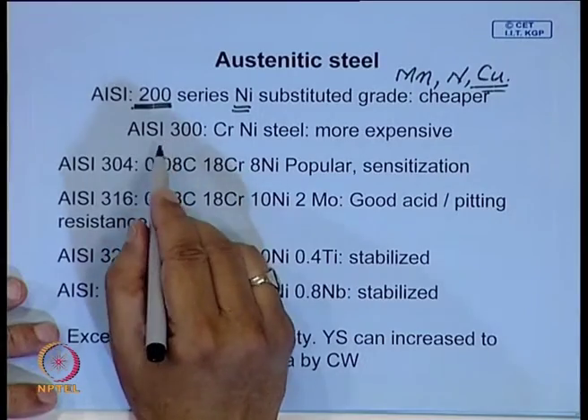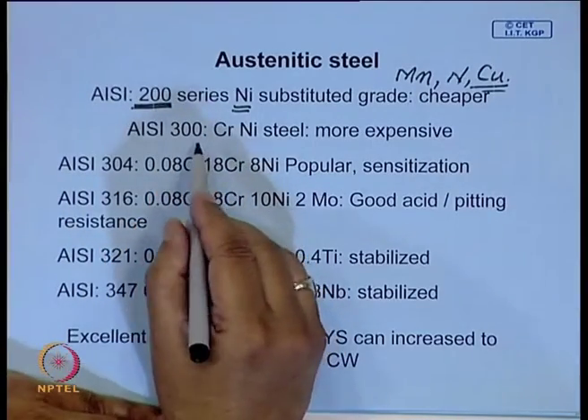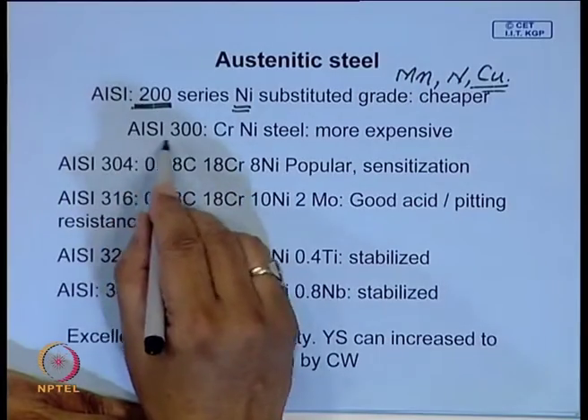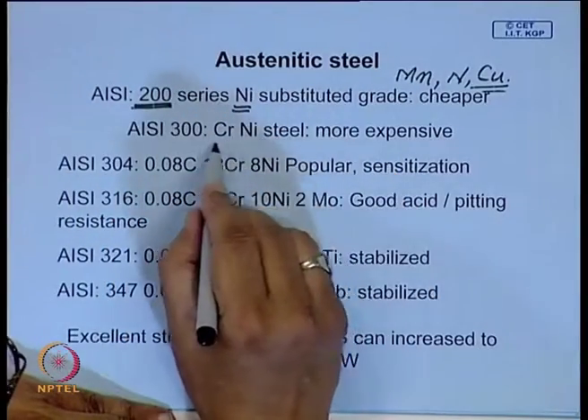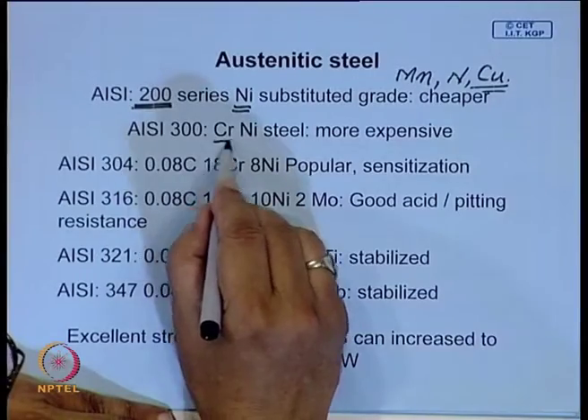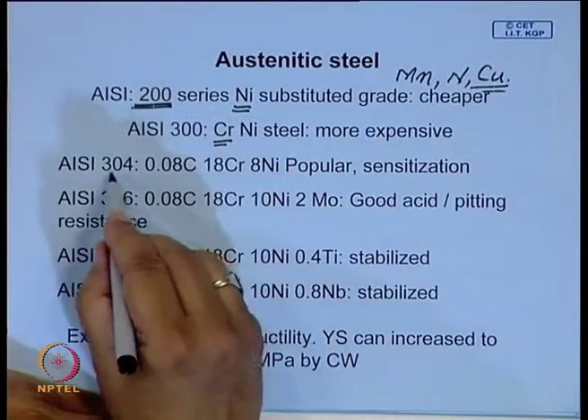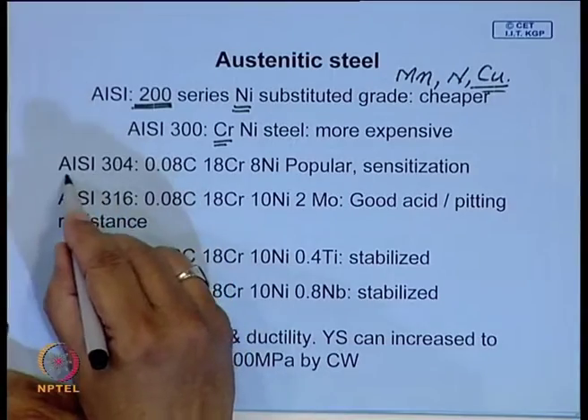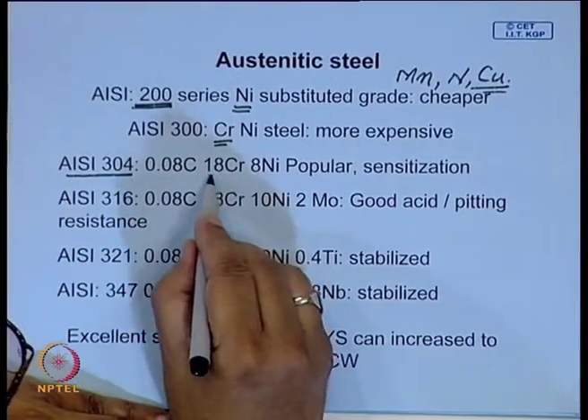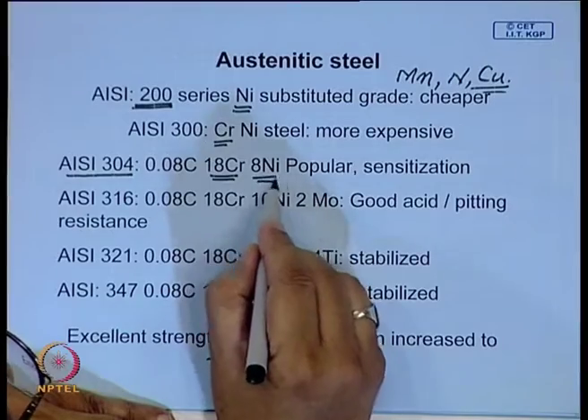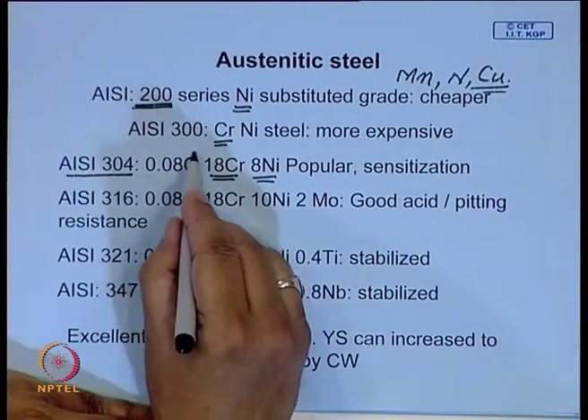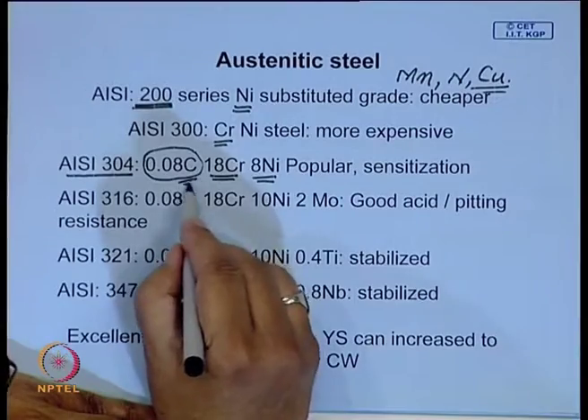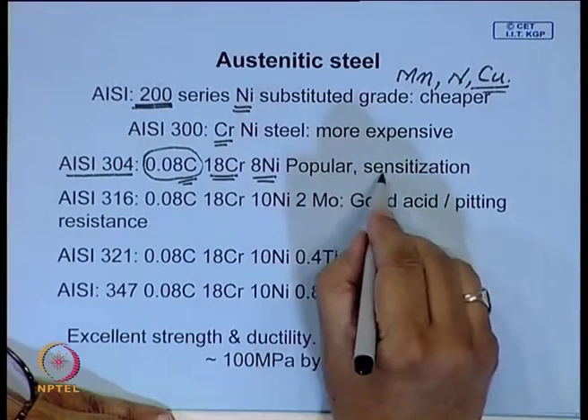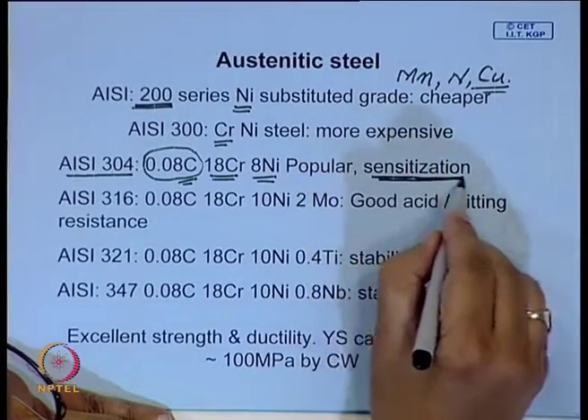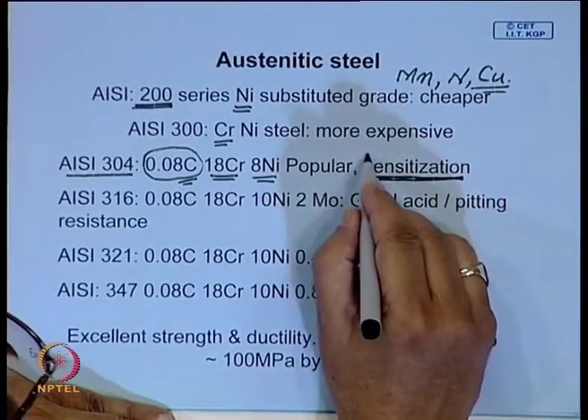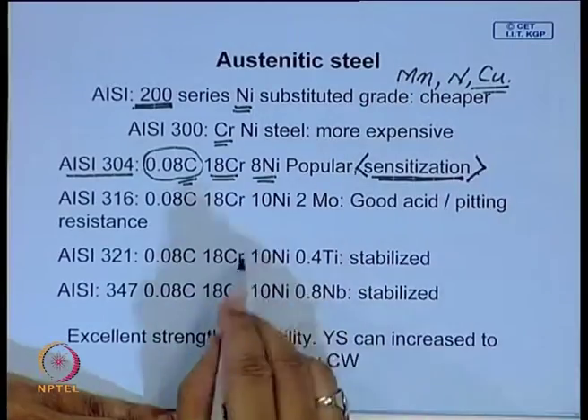Ferritic and martensitic steels are also stainless, but austenitic steels are definitely stainless, because they all have a very high amount of chromium. One of the popular grades, the most popular grade, is AISI 304. Here you have 18 chromium, 8 nickel, and it has some carbon content, and we will see the effect of carbon a little later, and this is responsible for a problem related to corrosion called sensitization.